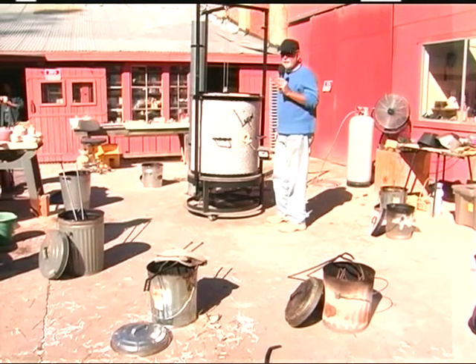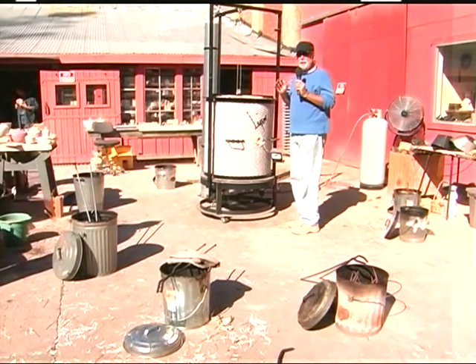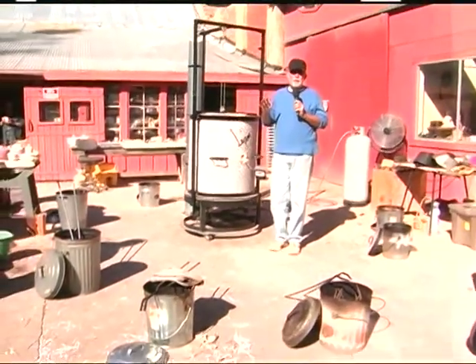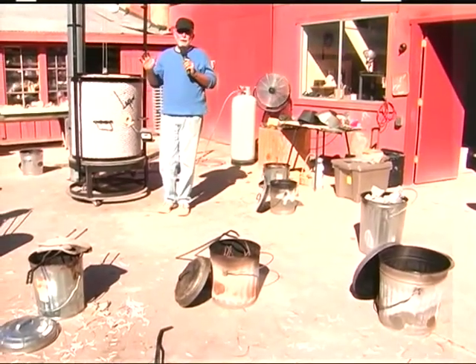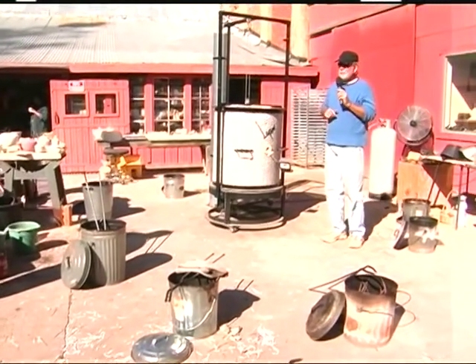In looking in at the pots that are on the top shelf, I can see that the glazes are somewhat bubbled, which means that they're still immature, they're still heating. When they get up to about 1800 degrees, they will turn bright orange and smooth over. When we see that, we know that they're getting very close. We give all of the artists an alert that we're a couple minutes away from pulling the pots. And then, as you'll see in a couple minutes, this place will be a frenzy of smoke and moving, flying arms and legs. So in a minute, we'll be ready to pull another couple hundred degrees.